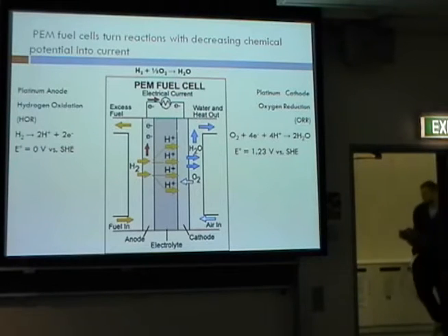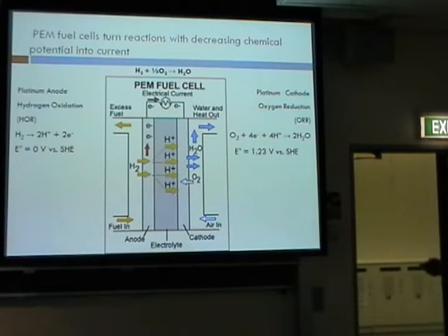All right, this reaction turns out that it has these 4 electrons and 4 protons being added. It's hard to do, and there are really 2 key issues in getting fuel cells to be more economical and therefore more viable in the long term. And one of those issues is that this reaction is not fast enough. And if it's not fast enough, that means you don't have enough current going through to drive your automobile, for example. Right? Since the rate at which this reaction takes place is directly related to the current that you're producing.